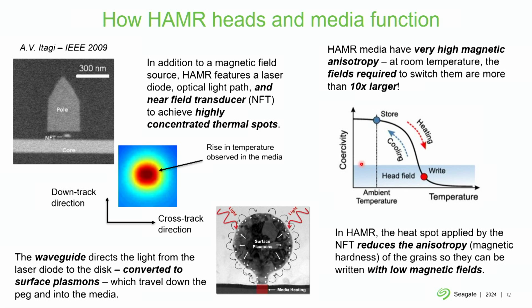So the media has to be different, and that's the whole point of HAMR. Now we can use very high anisotropy media. So this plot here is coercivity. So that's the field at which a sample will have effectively zero moment, which is a measure of how much field do I need to switch the magnetization of a material. For iron platinum, which is the material that we're using for HAMR, the coercivity is extremely high, over 80 kiloersteds, which is 10 times larger than that of what we're able to write with perpendicular magnetic recording. But if I apply a very concentrated thermal spot, then the coercivity is reduced to almost zero. And just enough to be able to write it with these fields that are applied by the magnetic writer.